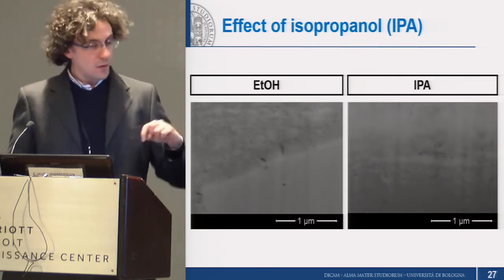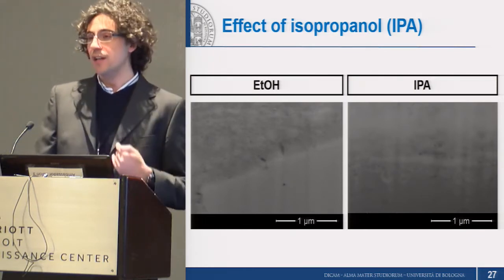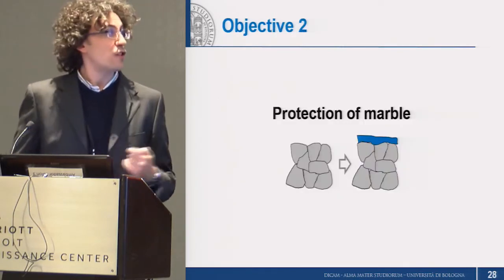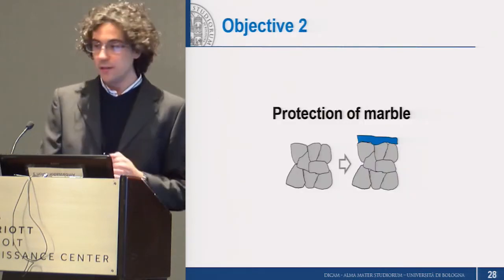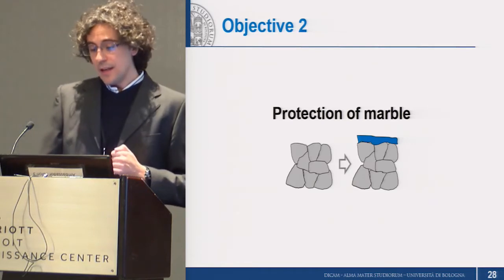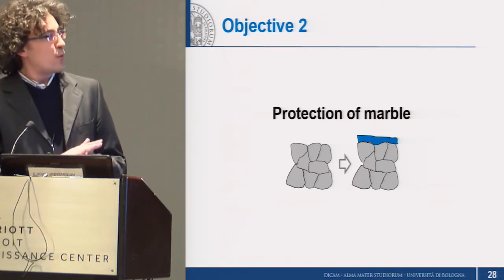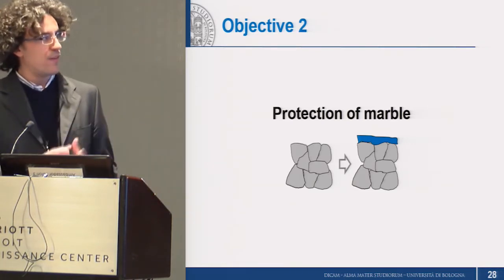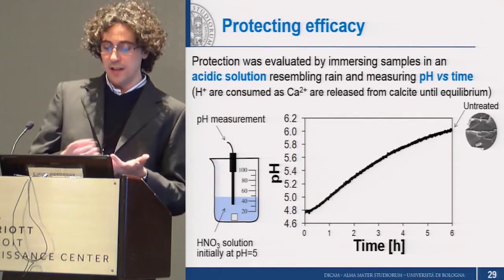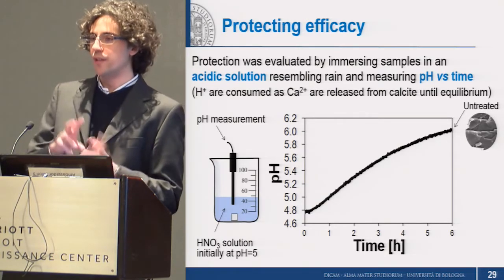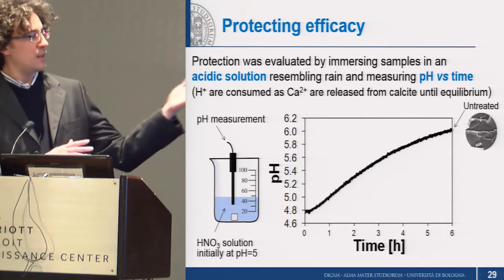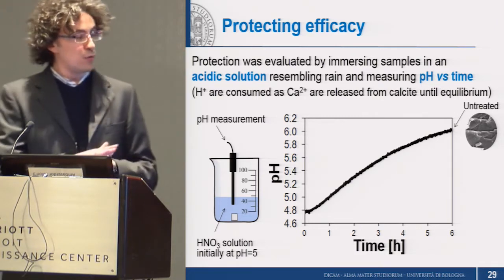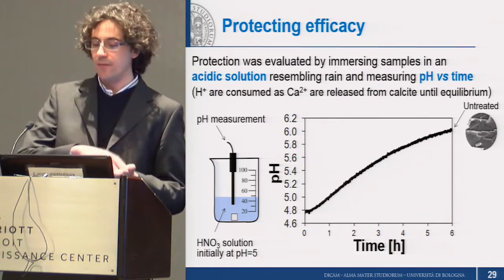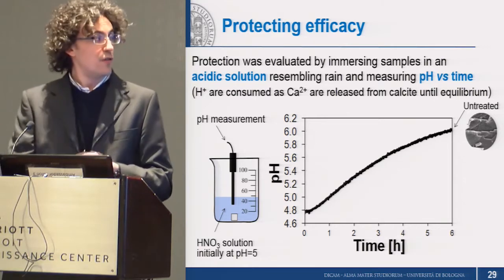So with all of this in mind, we started investigating the effectiveness of our treatment. First of all, in terms of ability to protect marble. We tested the marble protection by a simplified system setup, which is exposing our samples to a simulated rain, which is basically a nitric acid solution initially at pH 5, and then we measured the pH increase over time.